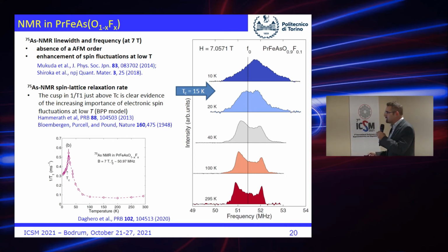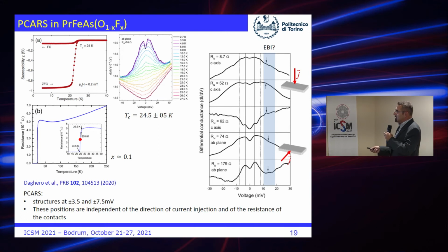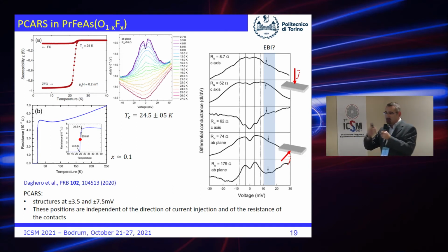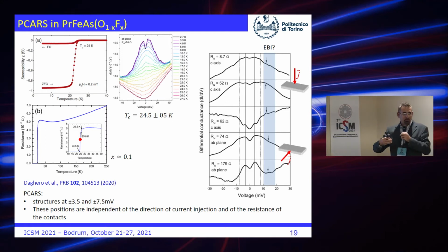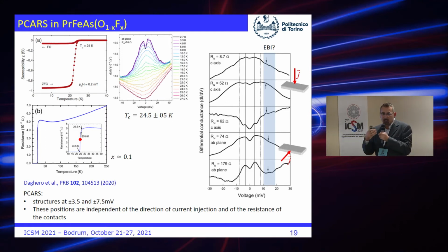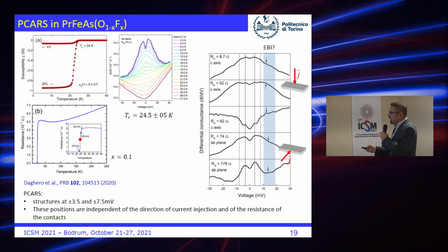Let us look at the spectra. Well, this is one temperature dependence of a spectrum. You see that the critical temperature of the junction is the one where the curves recorded at different temperatures start to overlap. You don't have any longer something that is decreasing. Everything is constant. And this temperature is of the order of 24.5 that falls very cleanly at the middle, more or less, of the resistive transition, and is also in agreement